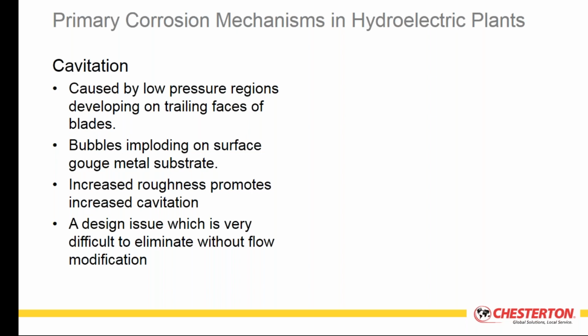First and foremost, though, it should be recognized that cavitation is a design issue. It's an issue that should not be counted on as being able to be eliminated by any restorative method. All you're doing is repairing the damaged area, but damage will occur again. It's very difficult to eliminate cavitation without impacting or improving your process flow to eliminate those low pressure regions.